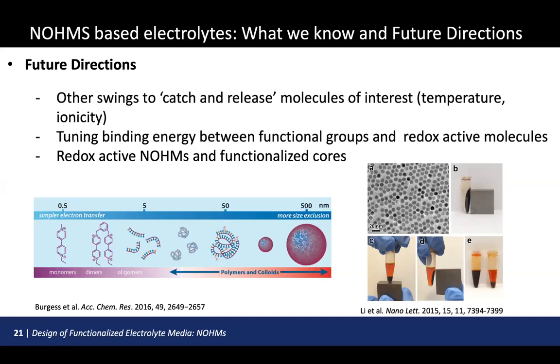And what we saw was that there is a multi-scale ordering of these NOHMs within the secondary fluid, depending on how much hydrogen bonding we have. So then we can tune that structure. If everything is evenly distributed, there shouldn't be overlapping of polymer to polymer because they're far away from each other. We put NOHMs in quite low concentration in terms of volume. But then when we looked at the actual interaction, we see in NMR and all these data that they do have interaction, which means that there is a clustering in a unique way, and that somehow enhanced the transport behavior.